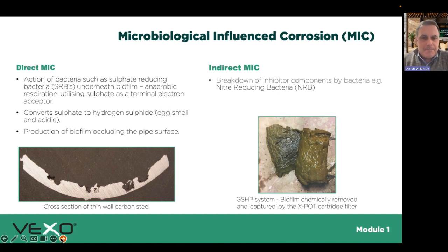giving it a dose of this bacteria. Once it's into the system under stagnant conditions, it will multiply. So the bacteria itself will create a biofilm eventually. This slimy looking goo, which you can see on the picture on the right hand side, that's actually a cartridge filter under there. And it's literally the layer of this slime that has just peeled off. This was a US military base in upstate New York. They were using a ground source heat pump system and having all kinds of problems. So yeah, and the other thing is they produce acids and you get smells as well. You typically know on a cooling system in particular, you get this horrible smell. So that's a concern, localized corrosion because of that, but also indirect will be the breakdown of any